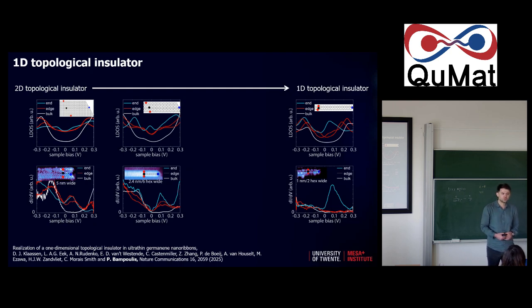But what we want to do is to find a way, in vacuum, maybe to take a crystal again or something, and then stamp on top of our crystal with another ribbon, and hope that we pick up some of them. If that works, then you could think of putting contacts and so on. I think the first step is simply to look with the pop-up STM, take these isolated ones, put contacts, use 2 tips as contacts and a third tip as a local gate, and see if you can do a proof of principle or concept device.